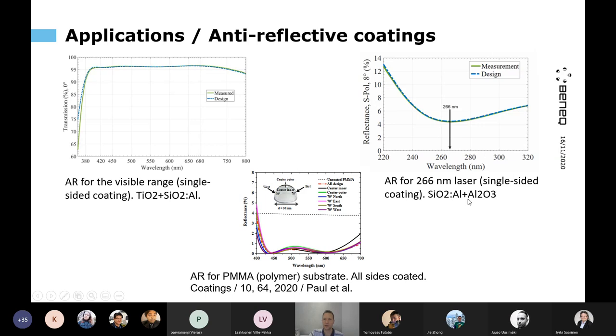And here's another example from the UV range, where in this case we used aluminum oxide as the high index material. It's not very high index, but anyway higher than silicon dioxide, and both are very transparent in the UV. Again, measurement and design are matching well.